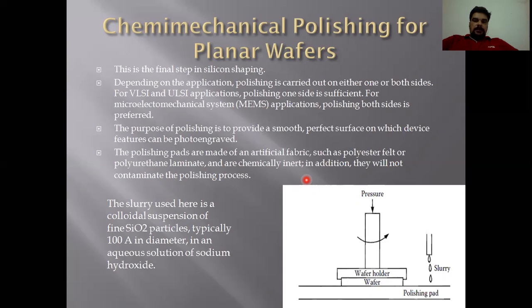So here, what is used? Here we are using a polishing pad. It rotates continuously, and we use a slurry that is deposited on the polishing pad. As the polishing pad is rotating, the wafer is attached to this polishing pad, and a certain chemical reaction takes place here, so that polishing is done.